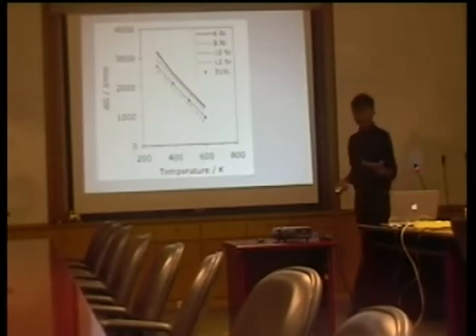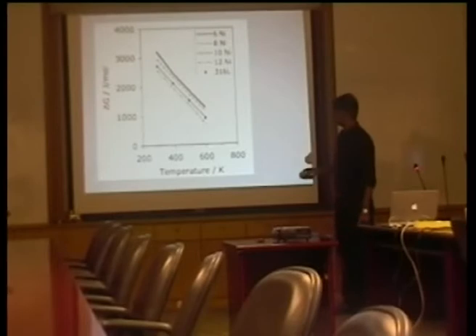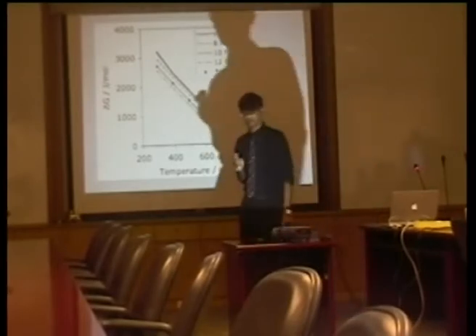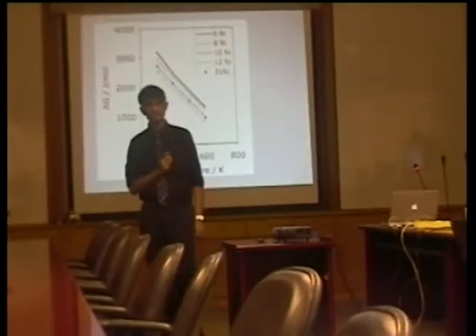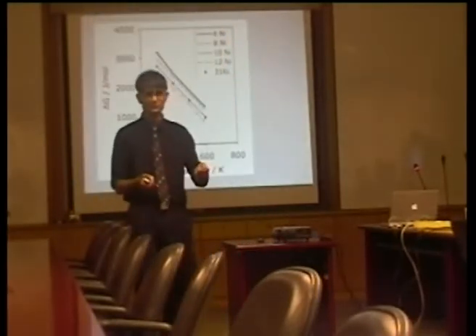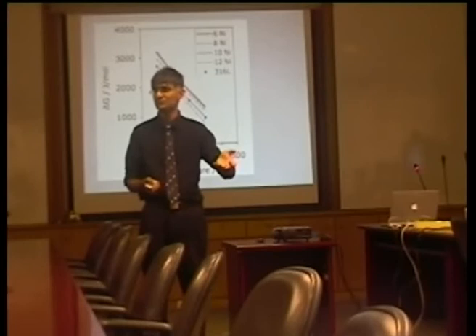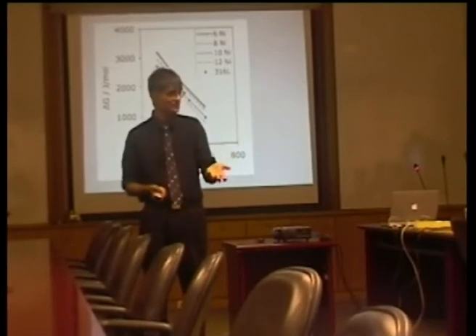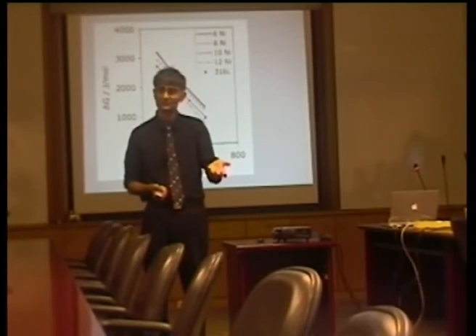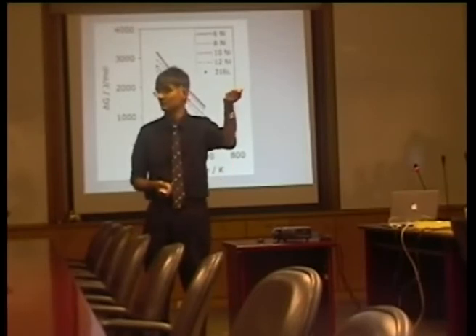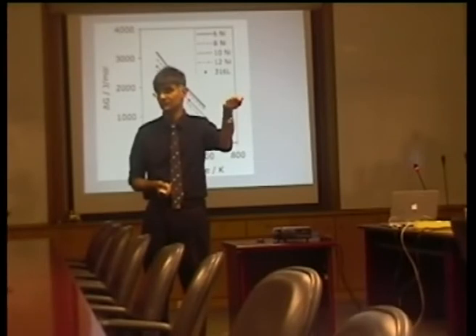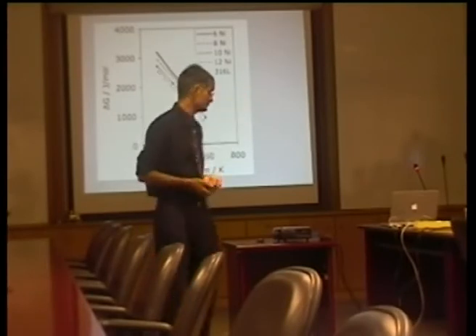Okay, so this is just to illustrate how the driving force varies with temperature. Of course, the other exciting thing is that we also have temperature in this theory. Because if I alter the temperature, then the driving force changes. So the stability of the austenite and martensite change as I alter the temperature. Austenite becomes more stable at high temperatures. More difficult to have martensite at high temperatures.